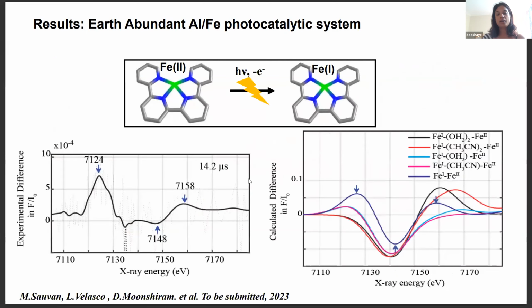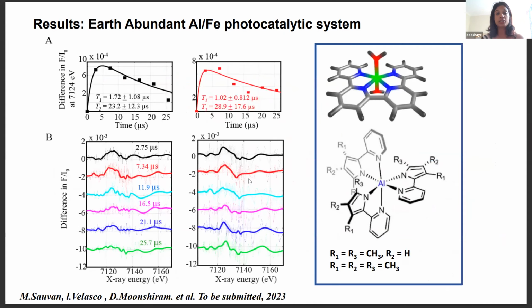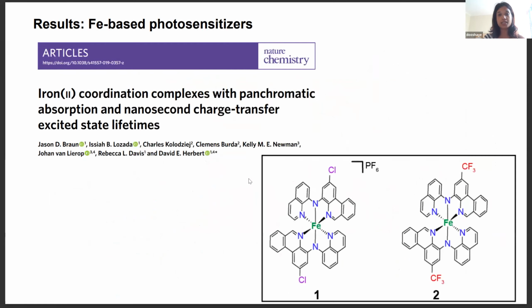Okay. And by comparing the transient signal with theory, we found that the photoreduced iron 1 adopts a square planar geometry. We also monitored the kinetics for the formation and the decay of the catalytic species. And we are currently investing more effort in iron-based catalysts that were previously reported in Nature Chemistry.